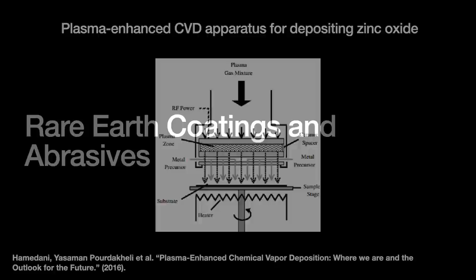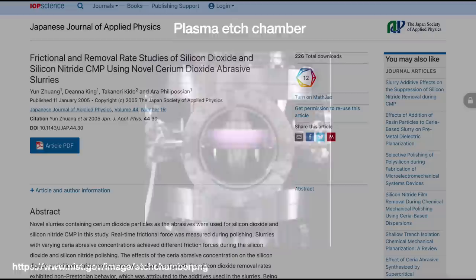One of the smaller but ever-present uses for rare earths is for coatings and abrasives — tracking these down in supply chains is a nightmare. We use a yttrium oxide-based coating for plasma etch chambers, which helps cut down on maintenance and cleaning costs. Semiconductor companies in China use cerium dioxide abrasives as part of chemical mechanical polishing, or CMP — a process for polishing the wafer down to an extremely flat surface for photolithography. It is called chemical mechanical because it has both a chemical aspect (a slurry with the abrasive) and a mechanical aspect (a polishing pad).